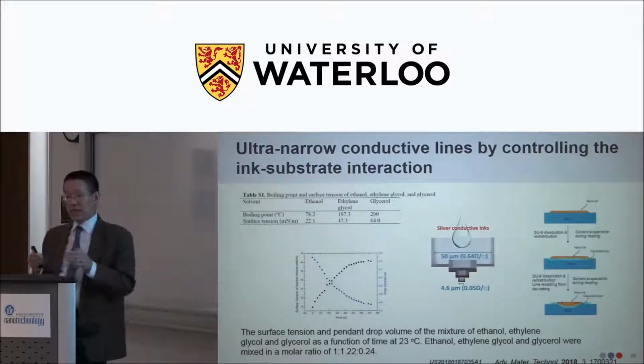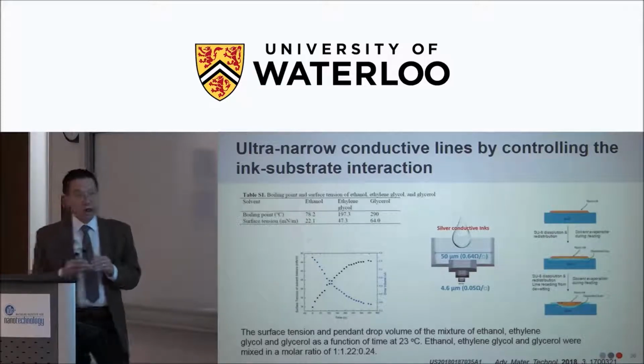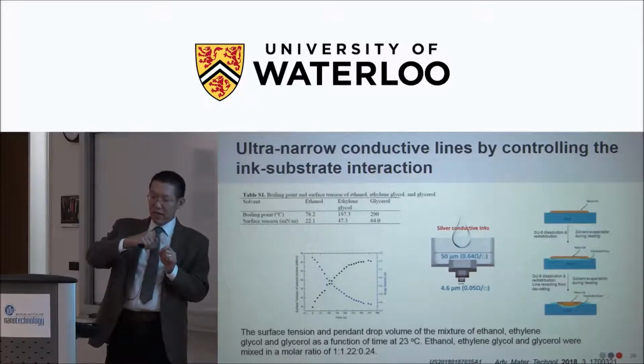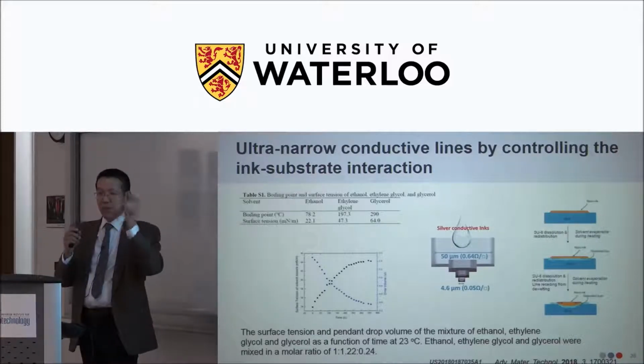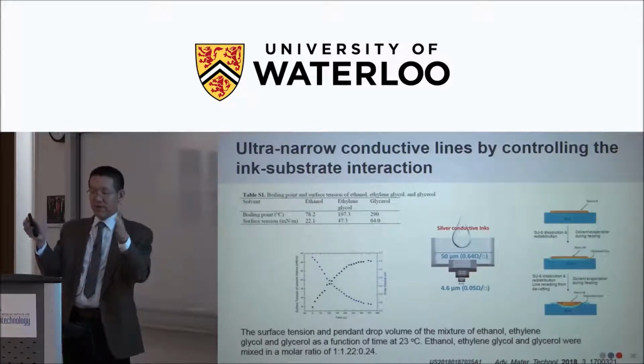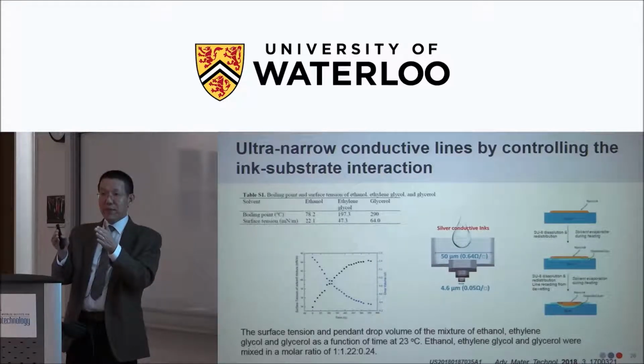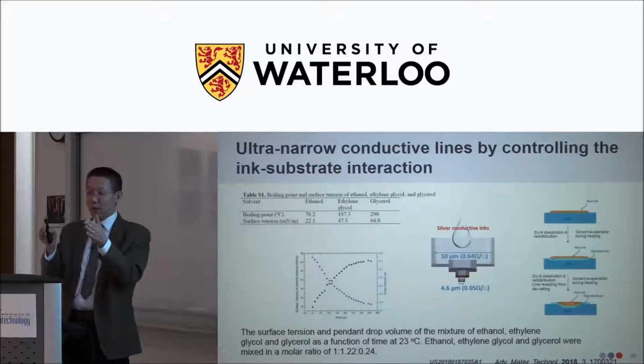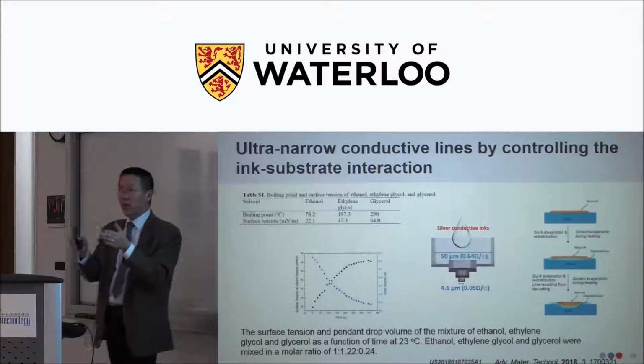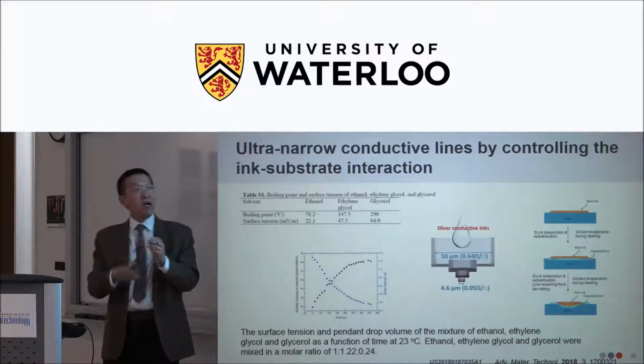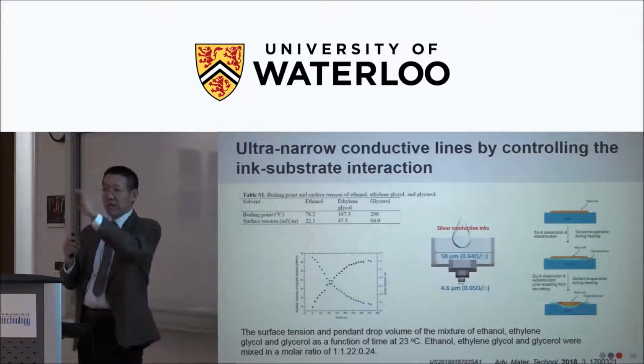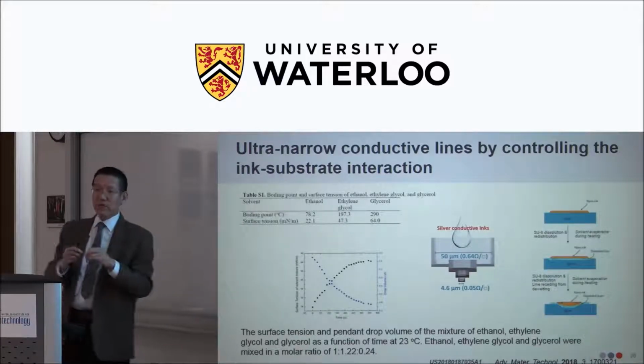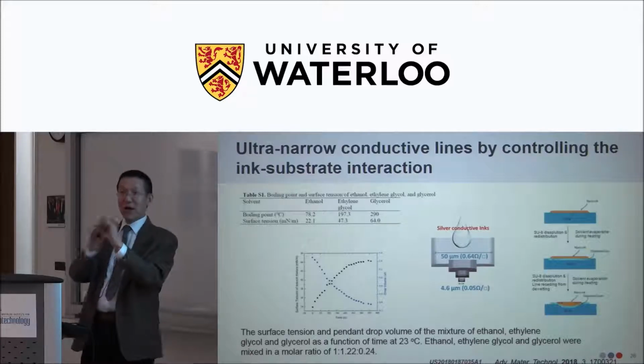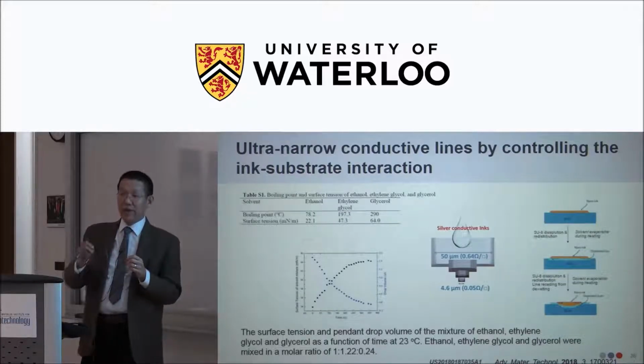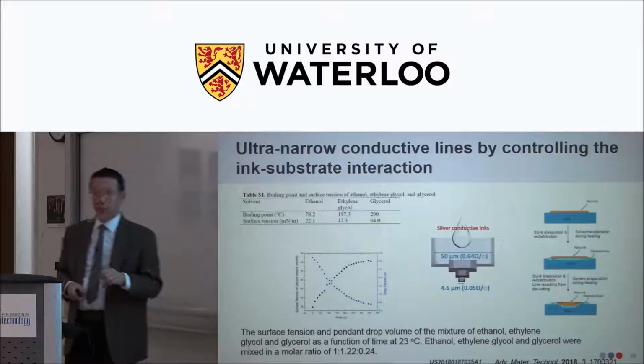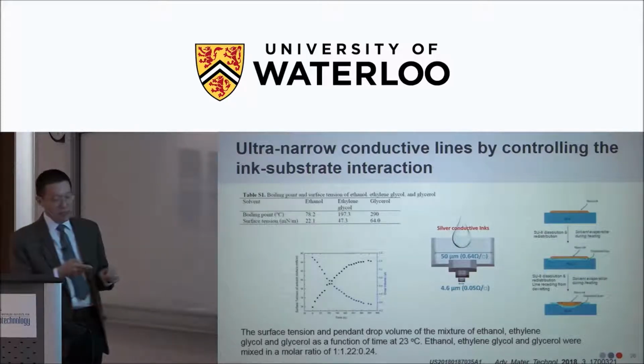So what we did here is that we tried to use the interaction of the inkjet printed line. When you dump the ink, you get 50 micrometer wide lines, but we shrink them. So the nanoparticles in the ink have nowhere to go but form a high aspect ratio line, almost like a cylindrical line. Because you shrink it, the total metal amount in the line is higher than reverse offset can print. So we get a very high conductance line.